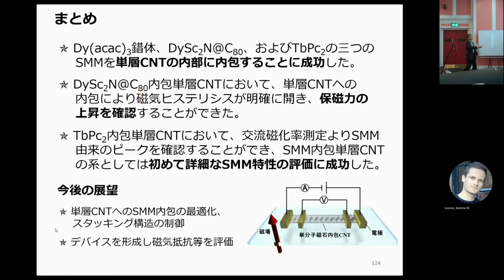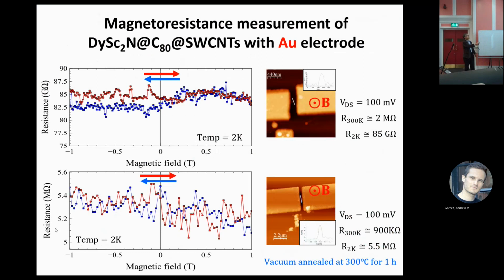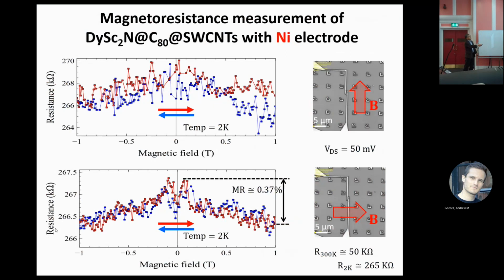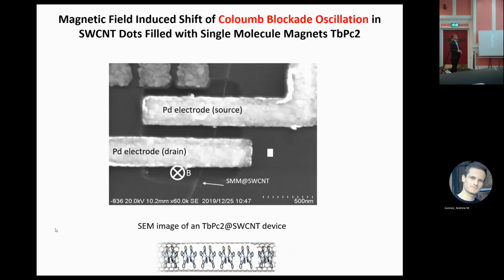So you can take one carbon nanotube and put the electrode by using lithography. Then we measure the magnetoresistance. So this is one carbon nanotube. This is a gold electrode, but no magnetoresistance. We switch from gold to nickel. You can see very small, but 0.37% negative magnetoresistance observed. This is due to the conduction electron and localized single magnet interacting. So then we realize negative magnetoresistance and also Coulomb blockade oscillation.